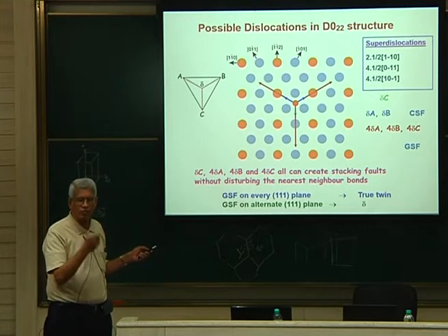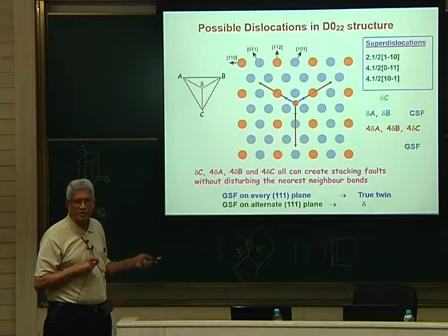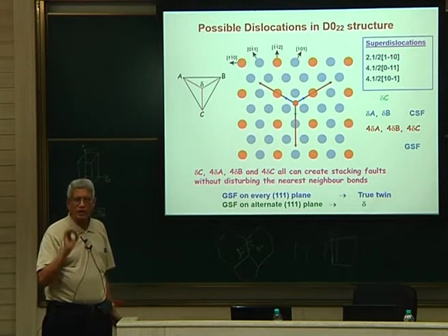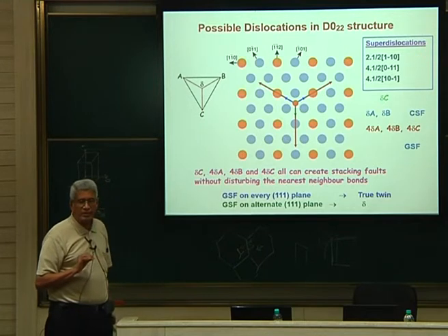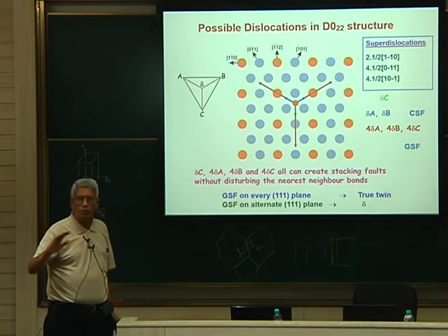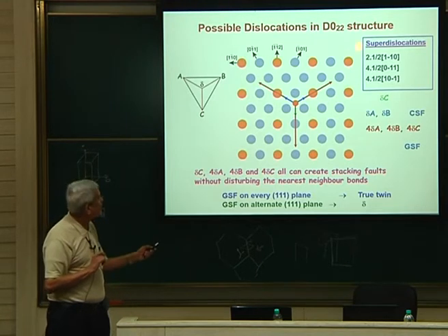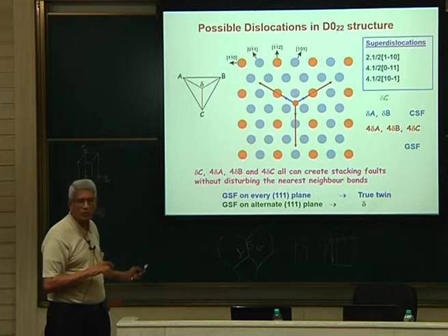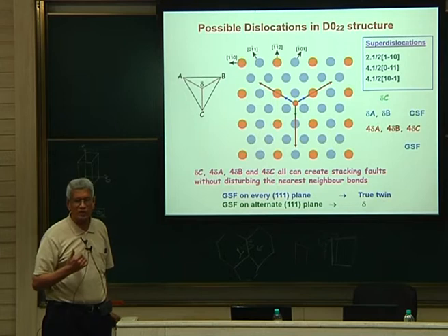And if you look at the self energy of the dislocations, it will always be less here for all these. So in short, in this specific direction, if you observe in the TEM, you should see pairs of dislocations, and in these directions, suppose the dislocations have moved, we should have 4 dislocations together.